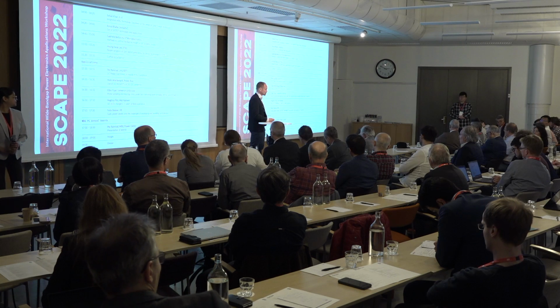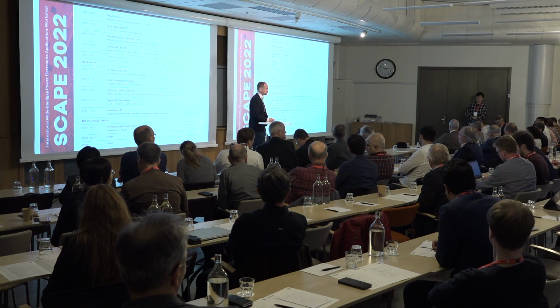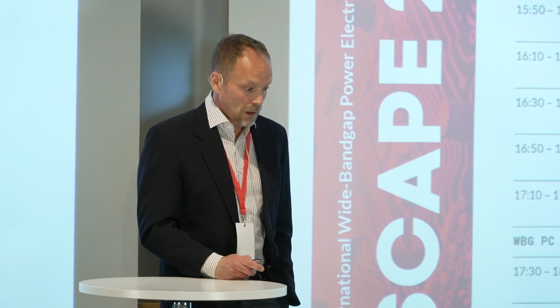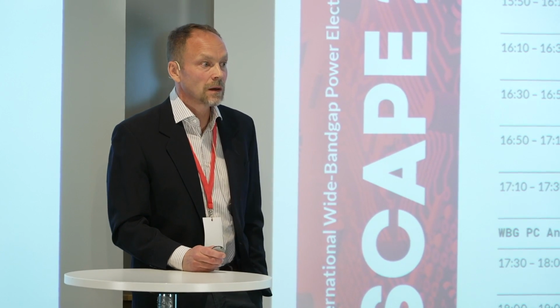Just one short question. Do you think that bipolar degradation is still an issue in your products? We have that ISiCPEAW paper, and we're looking into that also. We did binning of packaged devices with different numbers of BPDs. And our conclusion was that under reasonable DC current stress with reasonable current densities, we see very little RDS(on) increase. But going to extremely high current densities, we do see significant bipolar degradation. We expect this in any MOSFET. But for regular use, we see very little.